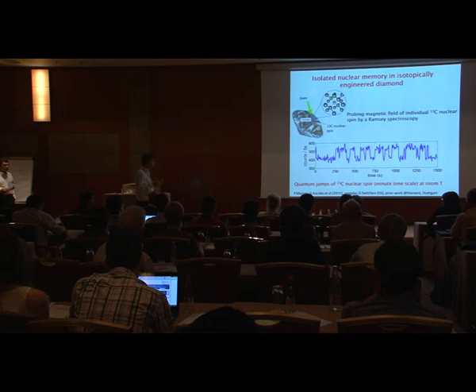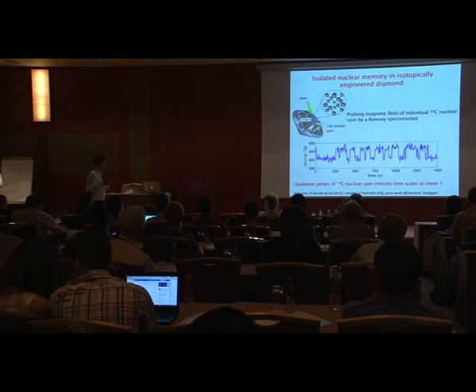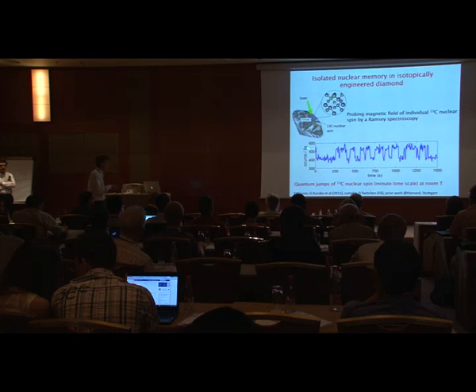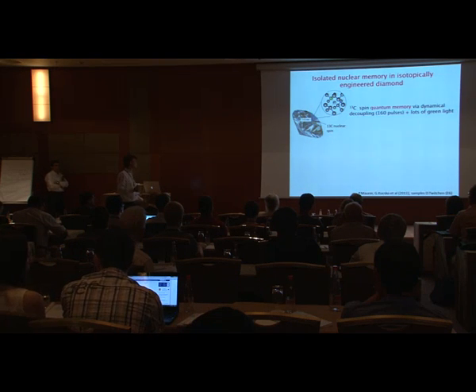So this is remarkable because we are now dealing with a system that is not isolated. It exists in a very complex environment. Yet it clearly displays quantum behavior with quantized jumps and clearly has a long lifetime. One can also ask how long the spin memory, the quantum memory, lasts in this kind of situation. It turns out that these quantum superpositions do not live minutes, but they can live for about a second. So this is a really long time for a solid-state quantum system under any conditions. But this now works at room temperature in a solid. So here is some perspective.